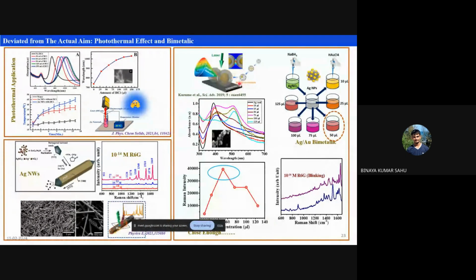So now we tried using two different plasmonic materials, silver and gold. Here I want to mention that the plasmonic property of silver is much higher than gold. But why can't we use silver? Because there is a very high chance that it will convert into oxide. So what can I do? I can prepare silver, then coat it with gold. Then it will not oxidize, and I can use it for the SERS activity.